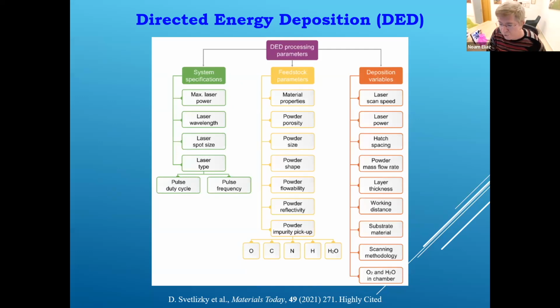Typically in DED, for instance, it is recommended that the powder be between 44 to 150 microns, and it has to be spherical. We usually use gas atomizing. And then on the right-hand side, you have the deposition variables that you can adjust on the machine during the setup. We usually use, in my lab, design of experiments, Taguchi-based techniques, to identify the synergistic and the antagonistic interaction between the different parameters and the effect on the microstructure and the properties, for instance, the density and the mechanical properties of the parts.